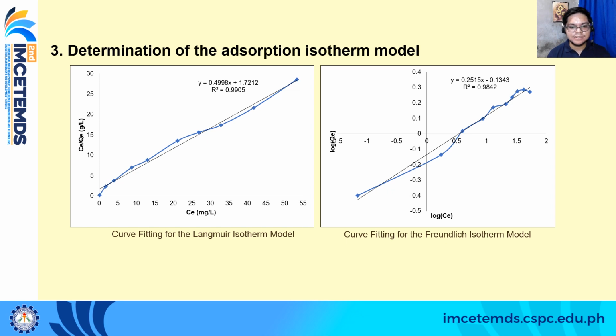Now, in order to optimize the use of our modified nanoparticles, it is important for us to establish the adsorption isotherm. The adsorption capacities of the modified nanoparticles were obtained at pH 11 and varying methylene blue dye concentrations. The data fitted well to the Langmuir isotherm model with a correlation coefficient value of 0.9905, as compared with the value of the Freundlich isotherm model. The Langmuir isotherm model is based on the assumption that the adsorption corresponds to a saturated monolayer of solute molecules on the adsorbent surface with no lateral interaction between the adsorbed molecules.